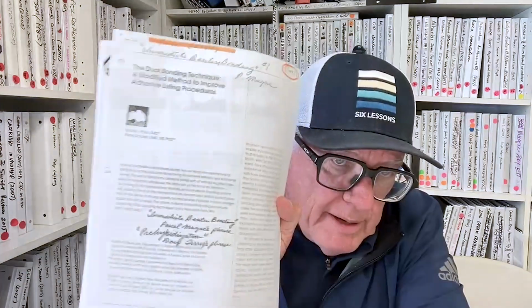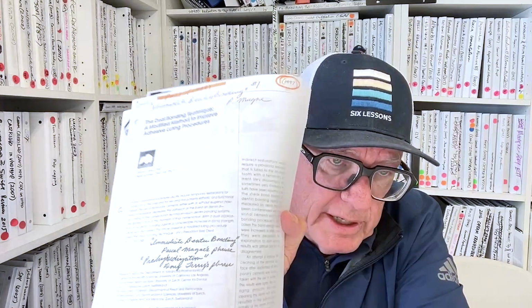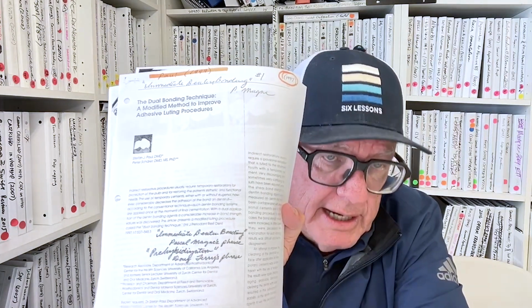Bill Liebenberg also called that pre-hybridization in 1999. But the idea of, in an indirect restoration or a semi-direct chairside restoration, to have a maximum interaction and bond strength, you have to hybridize that hybrid layer first and then wait a period of time. It may be 30 minutes to make the steric restoration, or it may be 2 weeks if the lab is making your indirect restoration. But the idea of this dual bonding means that there is a separation in time between the hybridization of the dentin and the cementation.